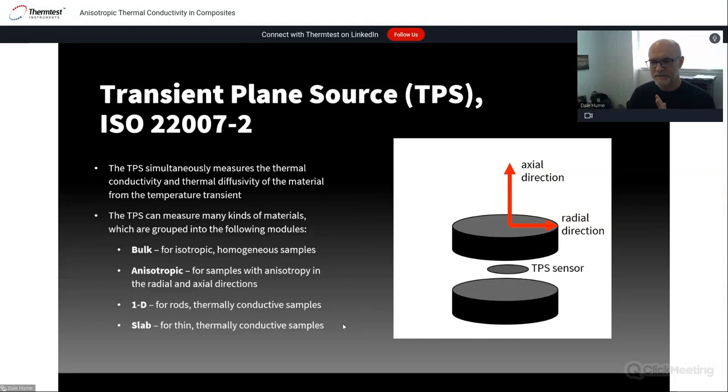So one of the approaches is to look at varying test times as you probe deeper into the sample. And if different test times give you different values, that's certainly a measure of the organization or the disorganization of anisotropy. Those are key tools that you can investigate. And of course, the typical approach is to measure as much of that sample as possible into the thickness so that if you do have disorganization, your values of axial and radial are accurate.